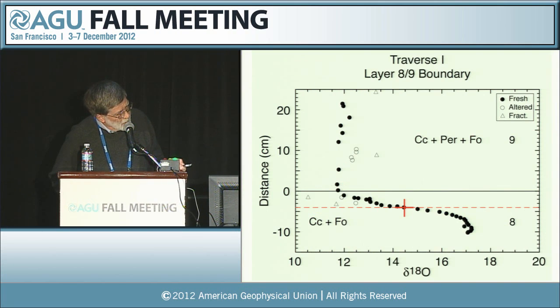Next, I'll show one example of this, from the layer 8-9 boundary. I've plotted the delta 18O value against the distance across the boundary. You can see pretty homogeneous delta 18O values within the interior of the Periclase-bearing layer. You can't quite see that so well in layer 8, but if there were more data, it's pretty homogeneous within 8 as well. Then you see these very steep coherent gradients at the layer boundary that are just displaced slightly from the layer boundary. But again, very coherent, so these are going to have pretty low values of dispersion.